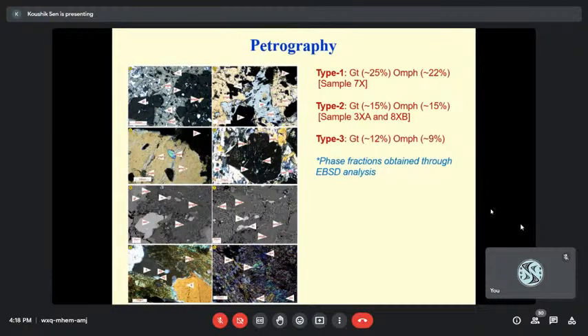And then finally, very retrograded or type 3 eclogites, where the omphacite phase fraction is very low, and in most cases, in the bottom right of the photograph, retrograded minerals like actinolite and chlorite are formed at the expense of their high pressure counterparts, amphiboles and pyroxenes and all that. So basically, depending on the phase fractions of garnet and omphacite, we can divide them into three types. Mostly type 1 is very fresh, almost the least amount of retrogression, then type 2 is intermediate retrogression, and type 3 is very retrograded.